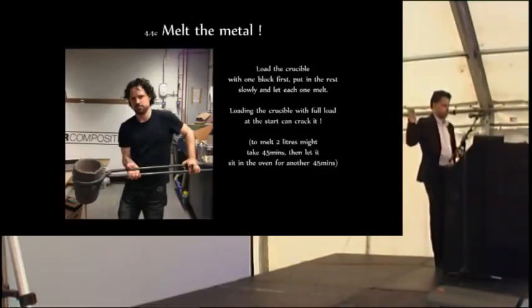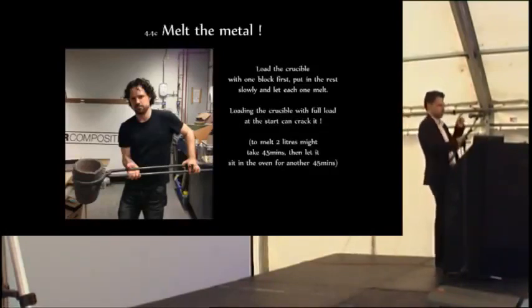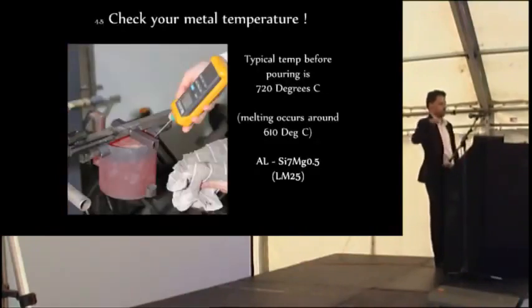Now, if you've listened to the first part of the presentation, you've bought yourself a thermocouple reader with a thermocouple. So you stuff that in and you check how hot the metal is. If it's the wrong temperature, it won't cast very well. So basically, you should heat it to about 720 degrees. If you heat it much hotter than that, it'll take a really long time to cool down, and you'll end up with a rubbish casting because it'll be oxidizing all the time it's hot. And if it's not hot enough, it'll solidify while it's pouring in. So you'll get your casting and find you've only got about half of it because the metal's gone solid before it's flowed in. So that's why you want to check how hot it is.